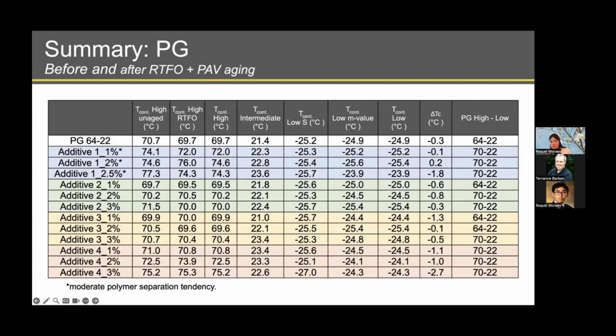The -22 remains. For the additive 2, the two higher dosages result in one grade bump in comparison to the base binder, jumping the high temperature performance grade to 70. And additive 3, only at 3%, we achieve one grade bump. And for additive 4, at the 3% dosage, the one grade bump was obtained. And as shown before in the graph for the low temperature performance, we saw that all the binders remain at PG minus 22 as the base binder.